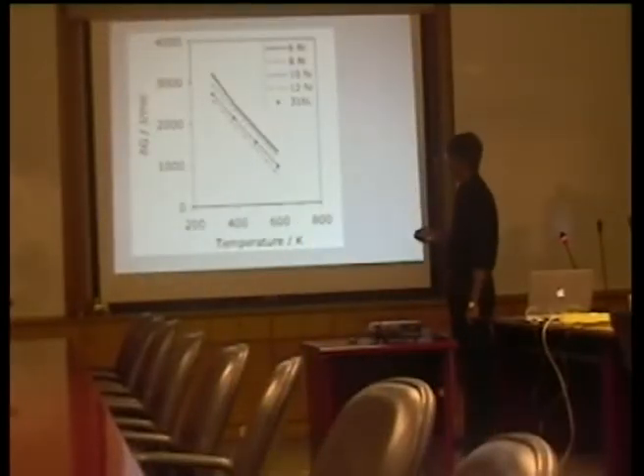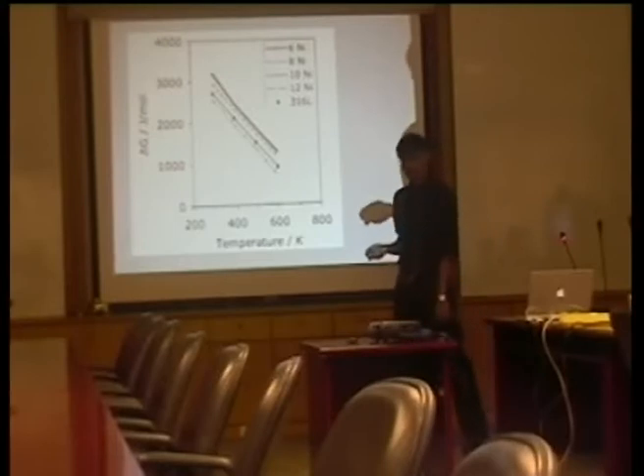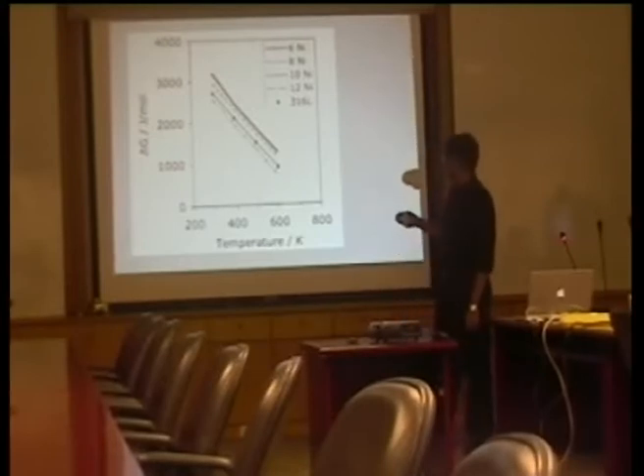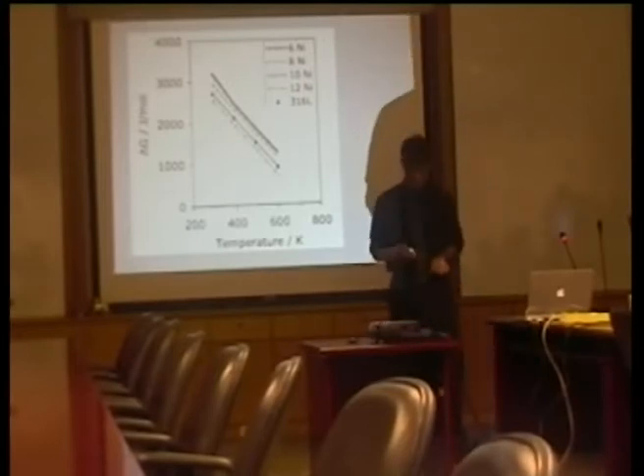So if you focus on just these four lines here, forget about the points, then you can see that by altering the nickel concentration from 6 to 12 weight percent, I make the austenite more stable because delta G decreases. By increasing the temperature, I also make the austenite more stable. Okay. Delta G decreases. These points are for the exact composition of 316L, and I just want to show you that it's almost identical to this alloy here, which is of an idealized composition.